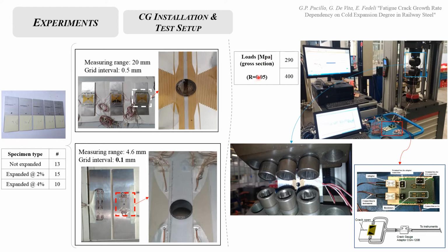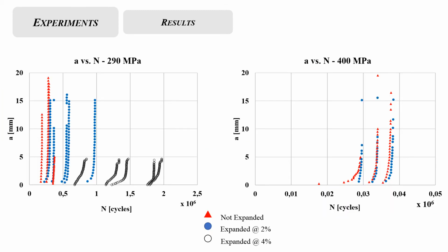Two load levels were chosen for the fatigue test, 290 and 400 megapascal, with a loading ratio equal to 0.05. Data acquired by crack gauges are reported in this slide for both load levels.